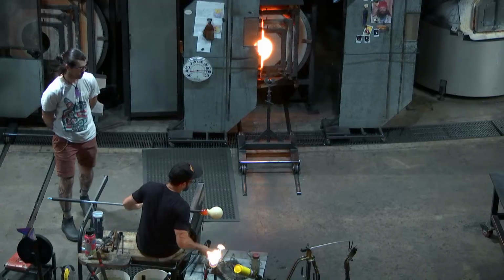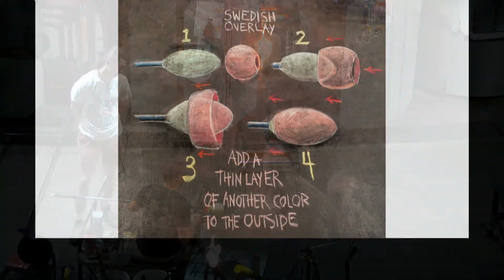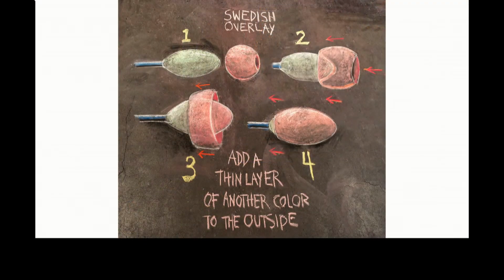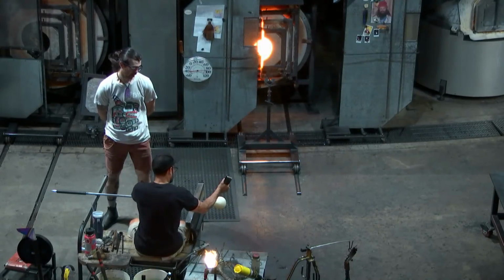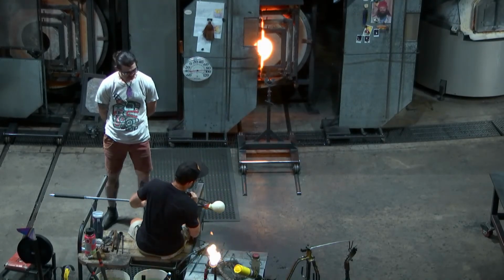If you do an overlay and encase it in clear, it's really hard to carve that color away because there's layers of clear glass on top of it. You'd have to carve into it really deep. So the Swedish overlay just makes it easier to carve directly into the color. This is the first step. They have to make the piece so that they can sandblast or carve into it later.